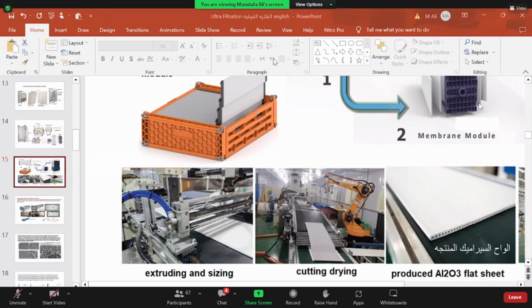But for silicon carbide, it is submerged coating. You take the plate, just fix 2 covers from both sides, right and left, to keep the holes or the channels inside, and then submerge it and take it out. So it forms just one layer of fine particles, 1 micron, for silicon carbide. For alpha aluminum oxide, it passes through 2 layers: one is the inner or middle one, around 5 micron, and the outer final layer, which gives the membrane its nominal size, around 1 micron, sorry, or even less than that.